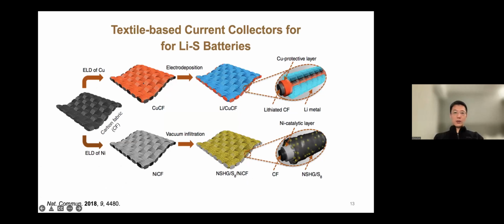So on the anode side, we use copper as a current collector, copper coated onto the carbon fabric. On the cathode side, we deposit nickel onto carbon fabric and use that as the current collector. The reason is that copper has a natural surface oxide and a high affinity to lithium metal, and therefore the deposition of lithium metal is pretty smooth. Nickel has a catalytic effect for the polysulfide, and therefore it can improve the efficiency and speed.